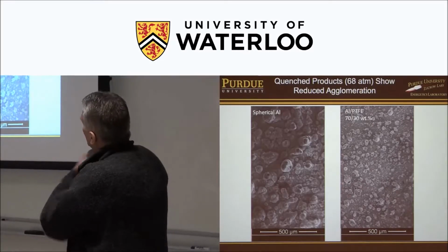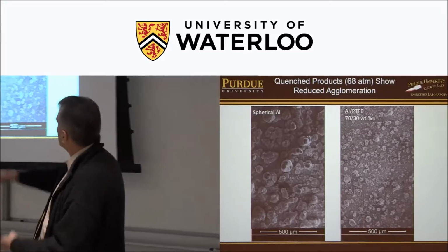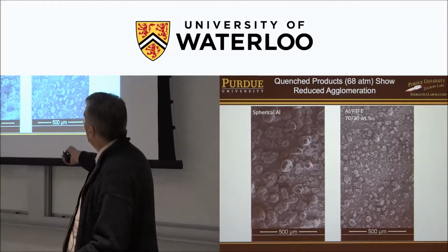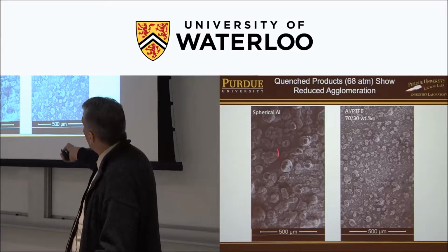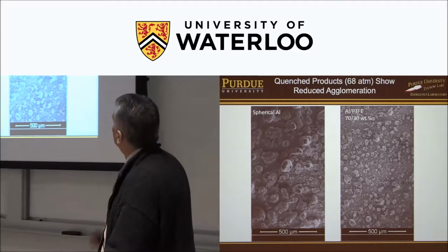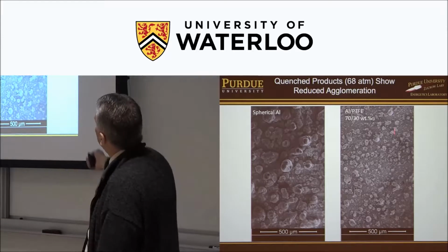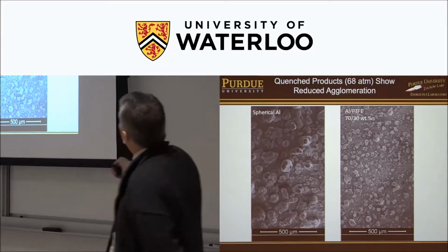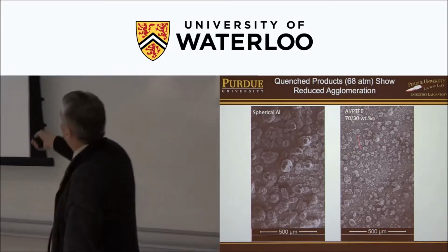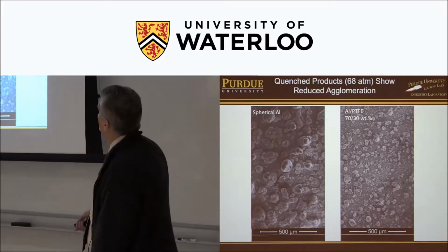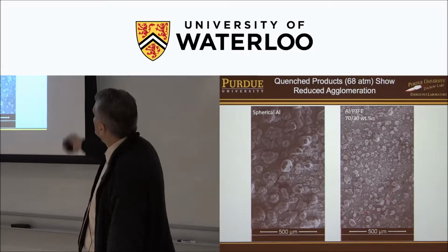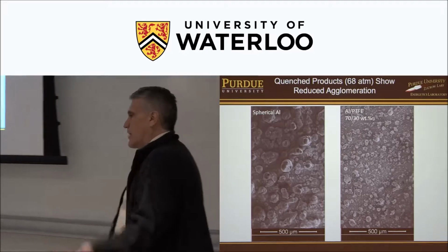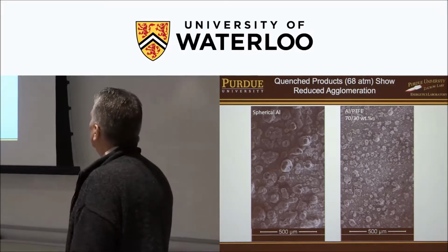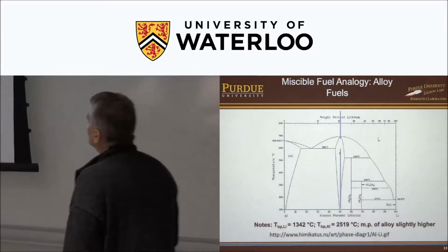This just shows we burn strands and collect the particles. This is the baseline propellant, and you can see the large alumina particles that we collect. For the modified, mechanically activated material, you can visibly see, and we've quantified this, of course, there's a lot smaller products. Smaller products will result in lower two-phase flow losses and better performance for your rocket.